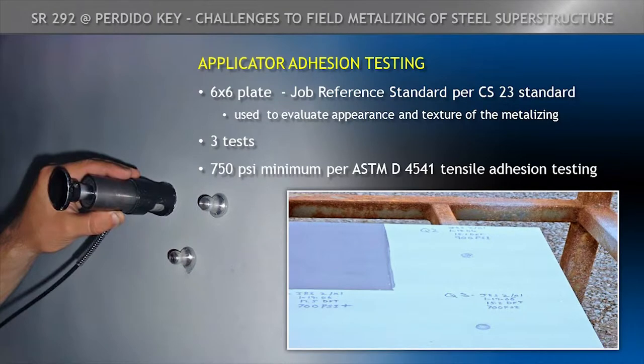They also had to do adhesion testing prior to being able to apply the metalizing to the bridge. And they did a 6x6 plate and 3 pull tests, and those pull tests had to achieve an average of 750 PSI minimum. The picture here is actually a job site reference we use. And we applied this to see what the blast should look like. We all agreed on the SP5 and clear coated it. And then we used this to do some pull tests. And we also used this plate to verify the type of texture we were looking for from the metalizing.